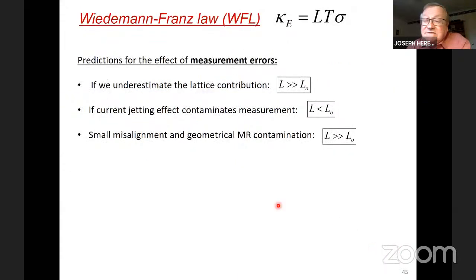So what is the influence of the measurement errors on the determination of the Lorentz ratio? Well, if we underestimate the lattice contribution, which is easy to do, then you would greatly overestimate the Lorentz ratio. If we had current jetting, and we don't, because we did everything that the Kava group said to do, or von Ohm's group said to do, we then have a Lorentz number that would be lower than L naught. But if we have an MR contamination, we will end up with gigantic Lorentz ratios, which are really fictitious. They're really due to extrinsic measurements, extrinsic magneto resistances that are contaminating the measurements of the chiral anomaly because of the slight misalignments in the sample.